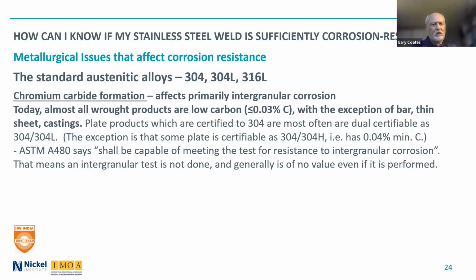Now, ASTM A480, one of the standards related to plate, sheet, and strip, has done away with doing the test for intergranular corrosion. It just says it should be capable of meeting it. The reason for that is that the standard intergranular corrosion test, the copper sulfate test, is so insensitive that it really is of no value. When I worked at a bar mill, the only thing that failed it was material that we had not annealed. So if we had annealed it even poorly, it would pass. So it was a lousy test. It wasn't a sensitive test. So that's why they have eliminated it as being mandatory. Some mills will still do it.